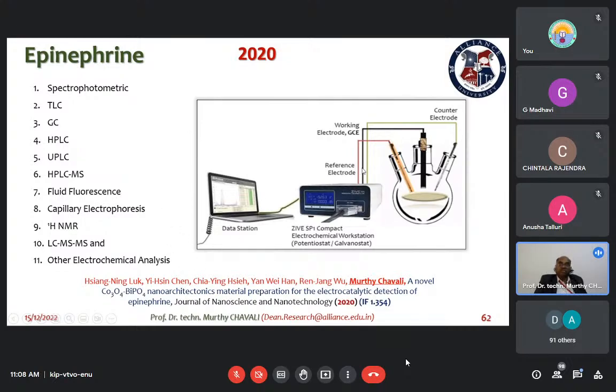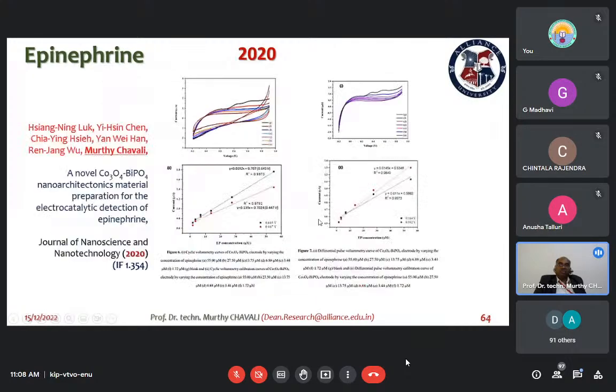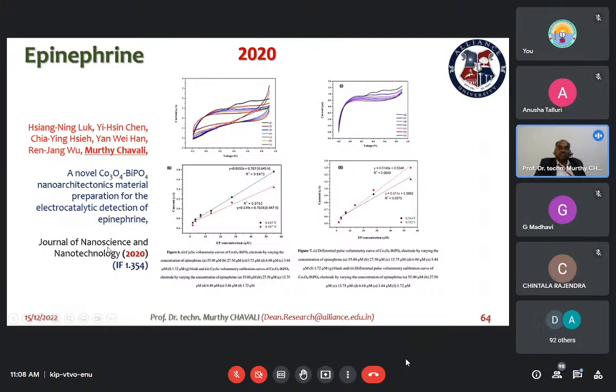So we started to work with some of the hospitals abroad, and we were able to produce some material based on dual metal oxide, bismuth oxide and cobalt oxide, but we failed in detecting this. Then we incorporated bismuth phosphate with the cobalt oxide, and we were able to develop an electrocatalytic oxidation method using a simple setup with an electrochemical cell and device, so that we were able to detect very low concentrations, something very close to 13 micromolar. With that, we were able to publish this in the Journal of Nanoscience and Technology.